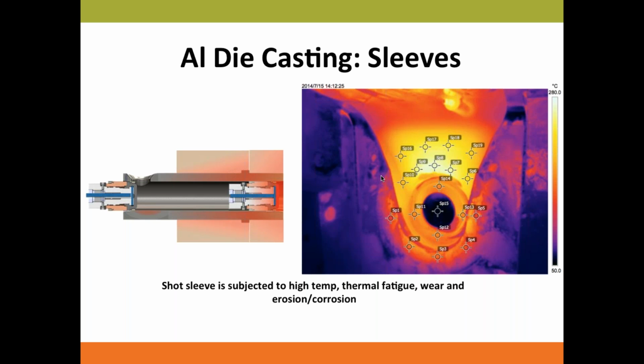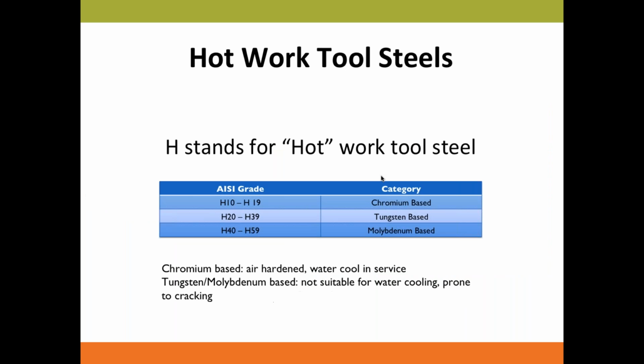So on the left, you can see a schematic drawing of a shot sleeve in a machine, with pistons or plungers moving from left to right, from parking to injection positions. On the right, when you open the die and shoot a thermal camera on the sleeves and the machine, you see the temperature distribution. You can see the temperature is pretty uneven. It can go as high as 300 degrees Celsius when the die is open. When the aluminum is actually touching the sleeve, the temperature can shoot up even higher than 300 degrees Celsius. So that limits our choices for the steels to work with for the shot sleeves.